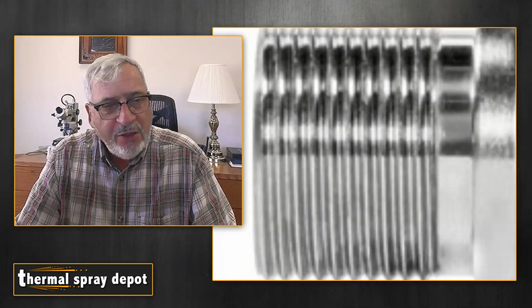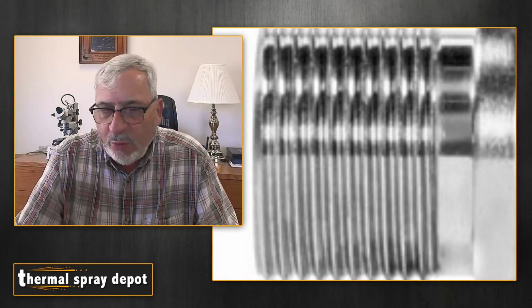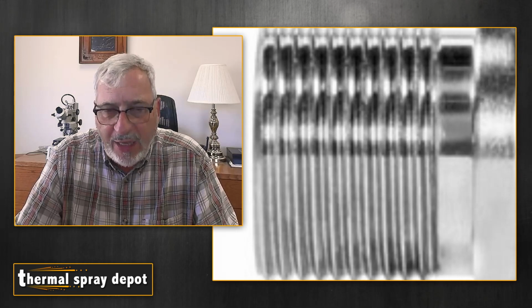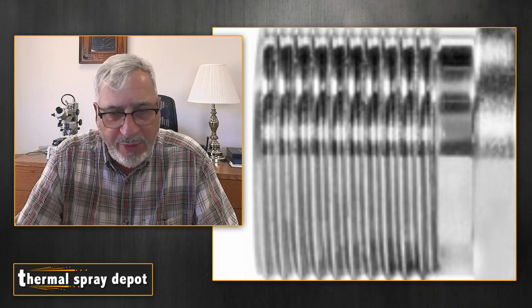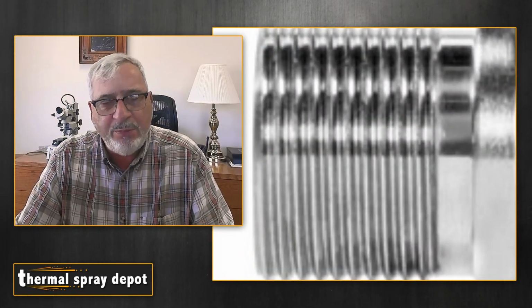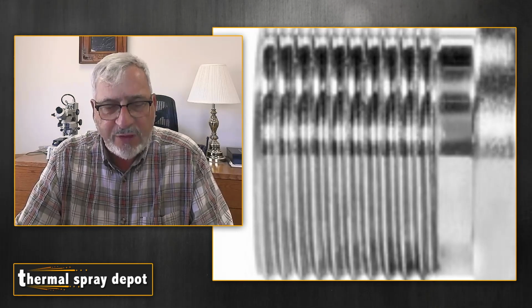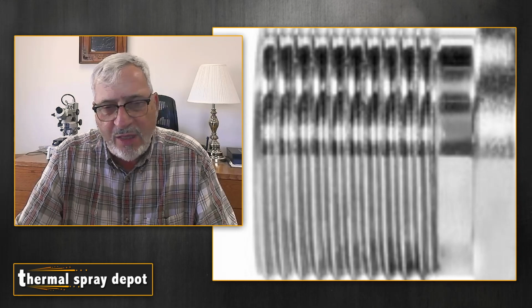So let's talk a little bit about surface prep. When we are prepping for spraying a shaft, and this is a good example, some of the old school techniques used to just do a thread on the shaft that you wanted to coat and do a buildup on. They wouldn't do any other surface prep than that. It worked in that when you machined the surface, if that surface prep was good enough and you had enough adhesion, the coating would stay on. So you did a test every time, so you had confidence that the coating was going to stay on. In a case like this where they're putting on a bearing or a seal surface, that was sufficient. And it's not the greatest way of doing it.